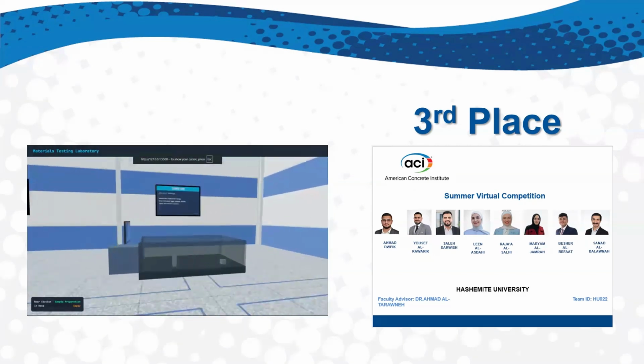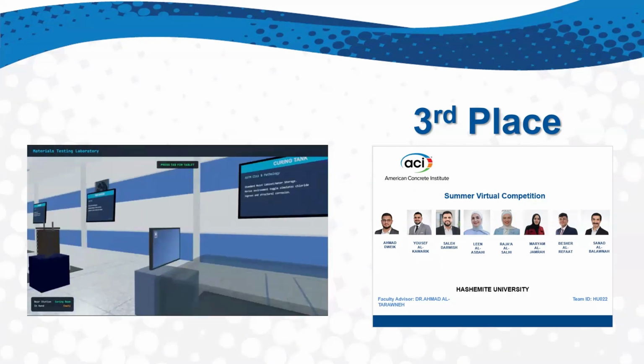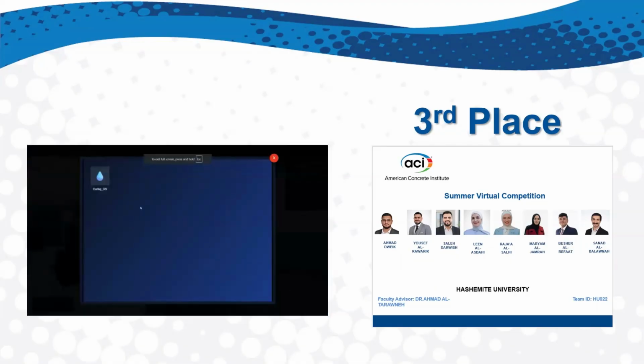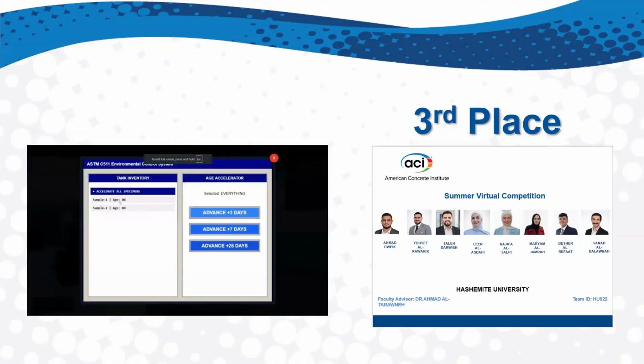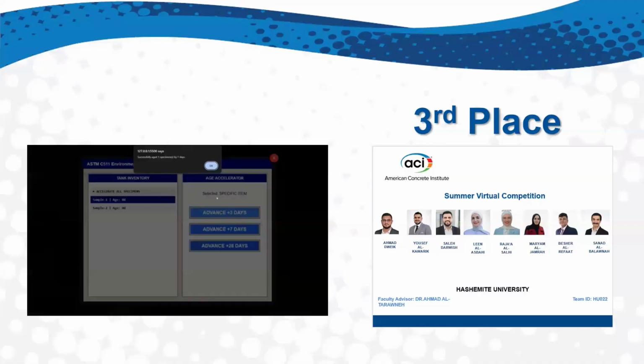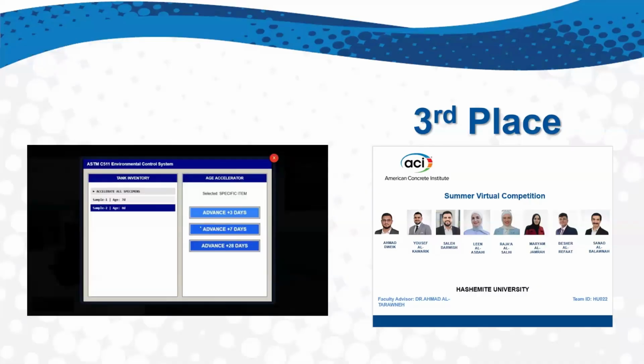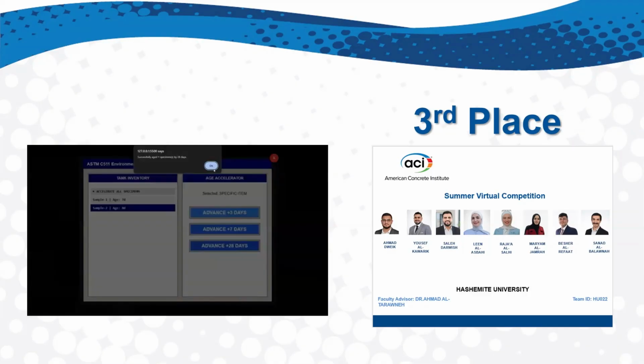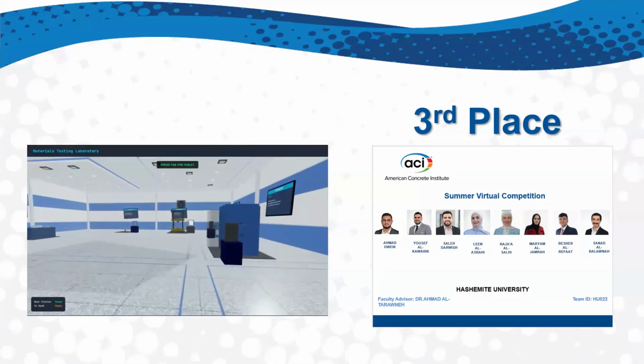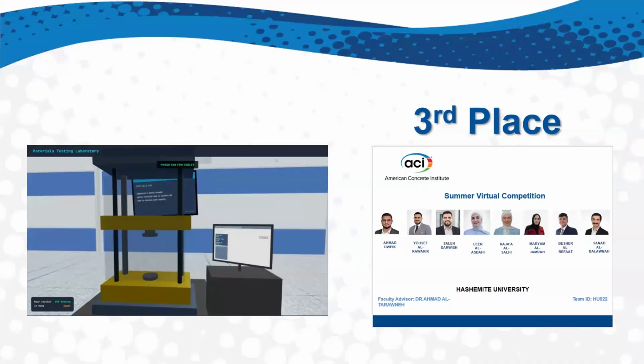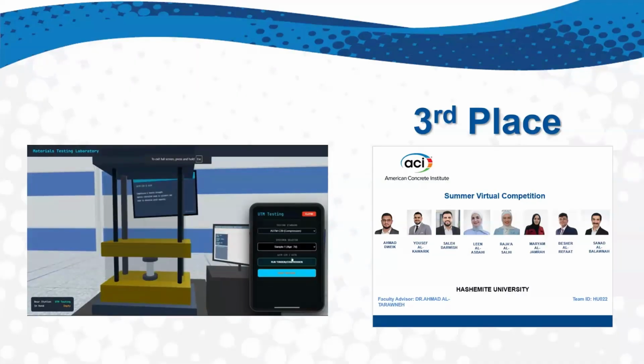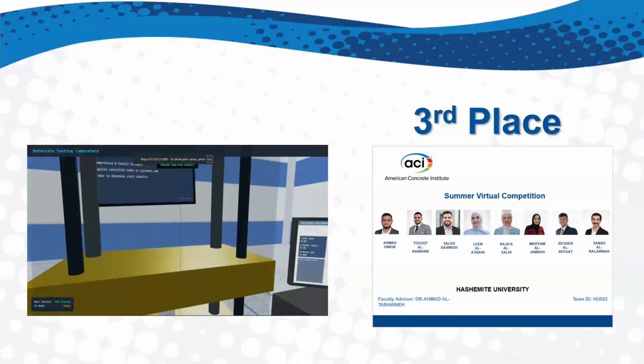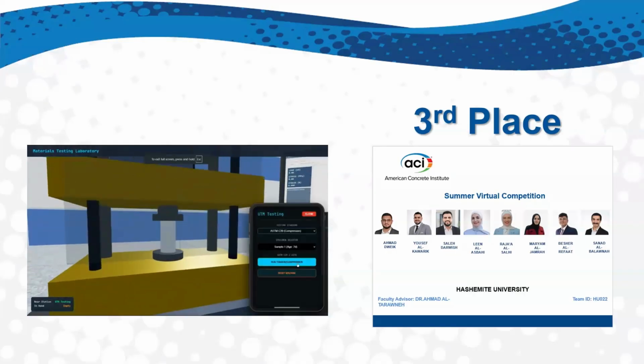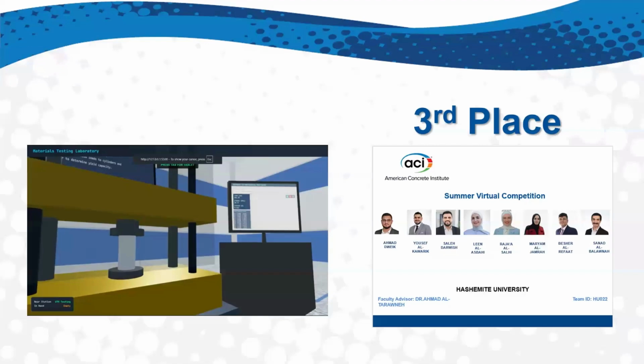Our samples, by default, are located in the water tank. We use the water tank to cure and age them. For example, for the cylinder sample, I'll age it for 7 days, and for the cube, I'll do it for 28 days. Now let's use the UTM to crush our samples. Firstly, let's do a compression test on our cylinder. Please get your eyes on the cylinder so you can see the cracks. Also, look at the monitor to see the curve, and at the end, you see the failure type.